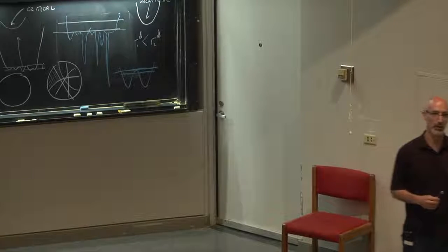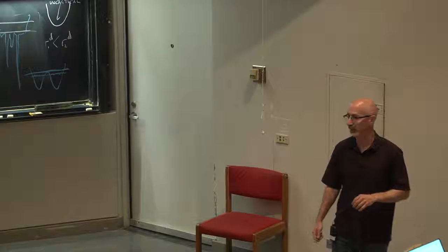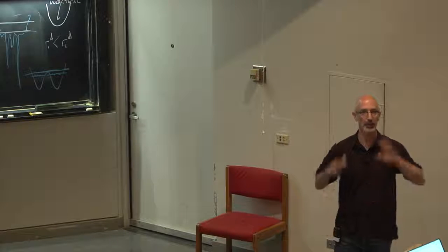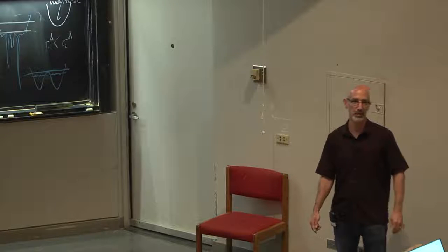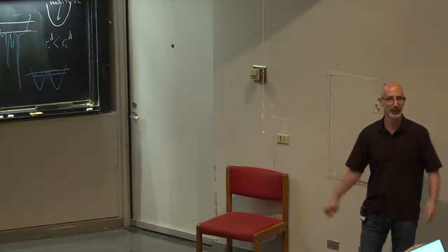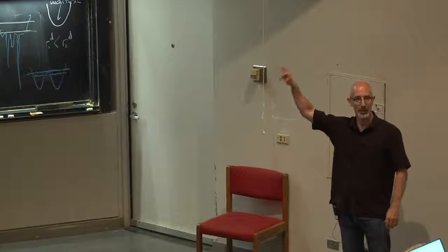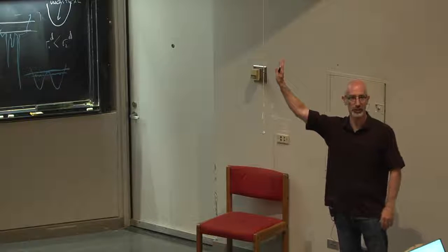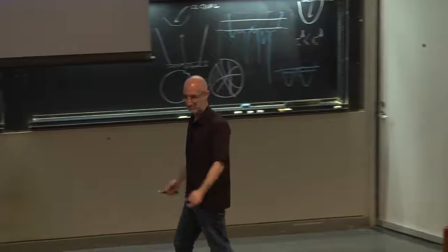I definitely know there's charge on the spheres, and I think the volume fraction here is something on the order of 40%, which, if you took a real hard sphere system at 40% volume fraction, is a Brownian system. So I want you to think of the system as effectively at a volume fraction of like 55%. They did some scaling of the volume fraction, but I don't know whether this was done right, and I do know that there's residual charge on the spheres. So you try to screen it with salt, but